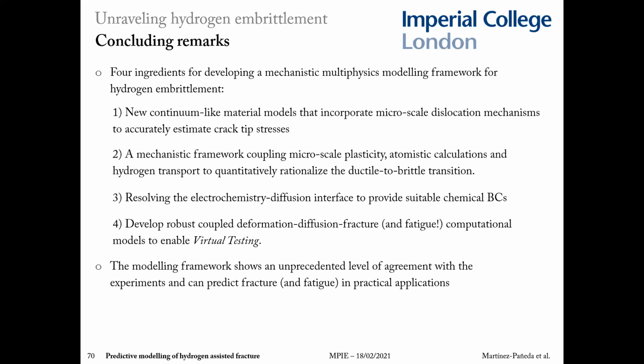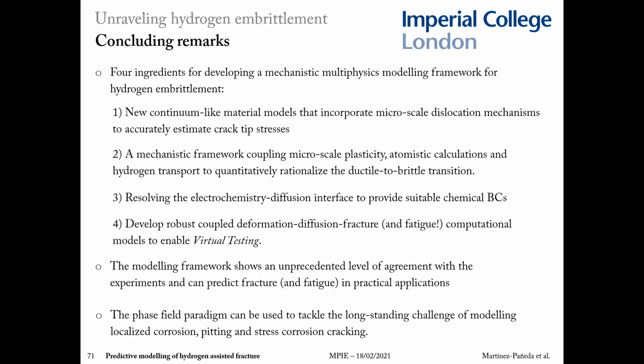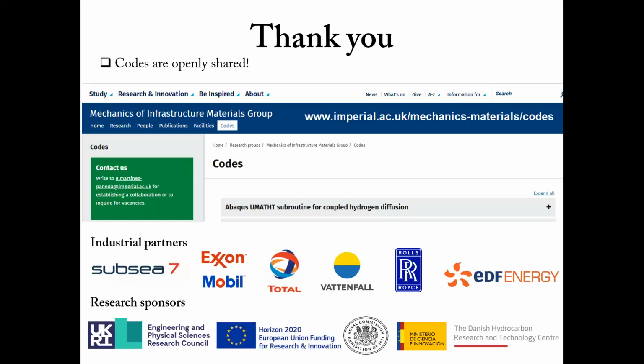And the good news is that once you put all those ingredients together, then things seem to be working nicely. And you have seen that we have been able to get a good agreement with experiments, that we have also been able to predict fracture and fatigue, not only in lab conditions, but also in complex engineering applications. And finally, we have shown that the phase field paradigm can also be exploited to model another long-standing challenge, which has also important technological implications, which is corrosion damage. And I think that we will see a revolution in this area similar to the one that we're seeing in fracture mechanics.